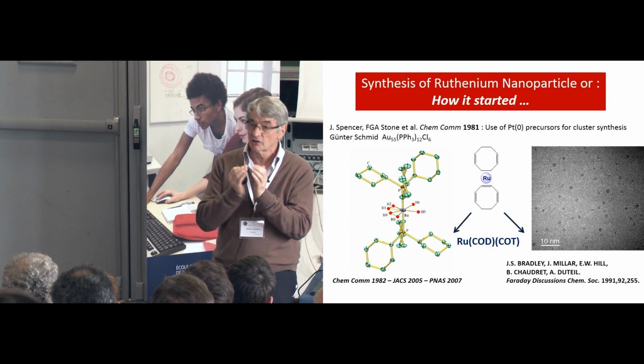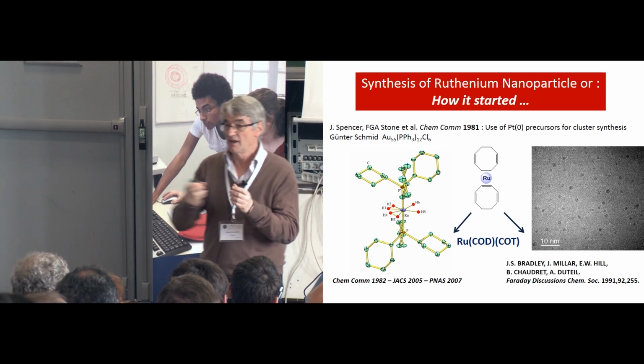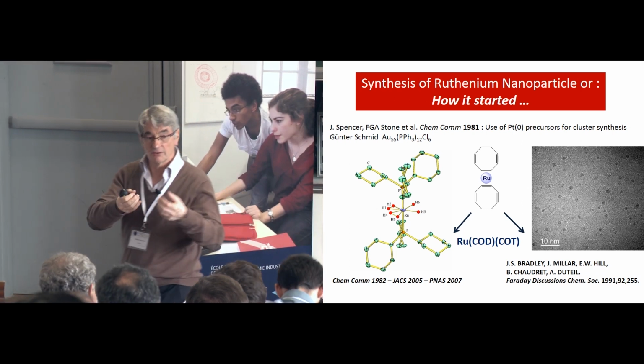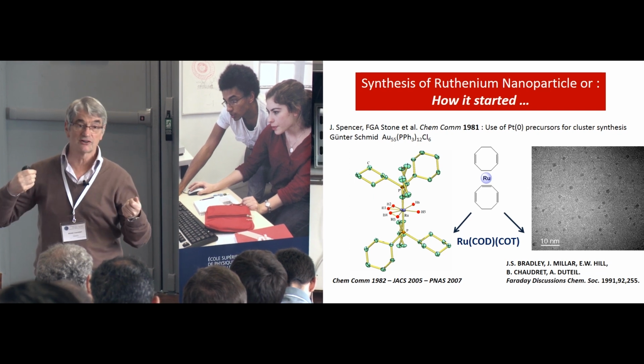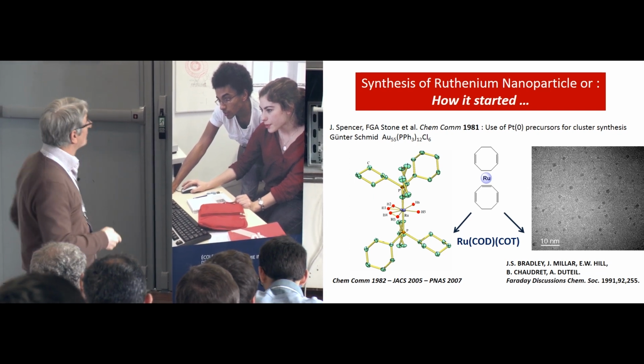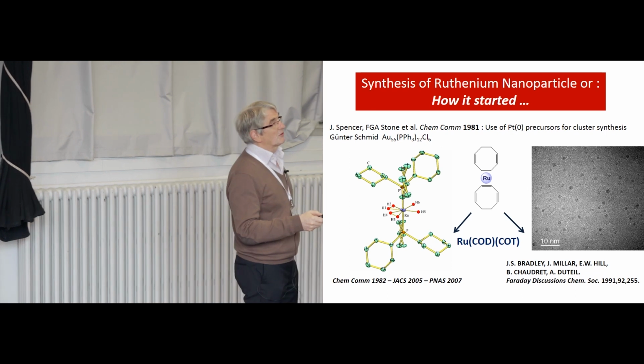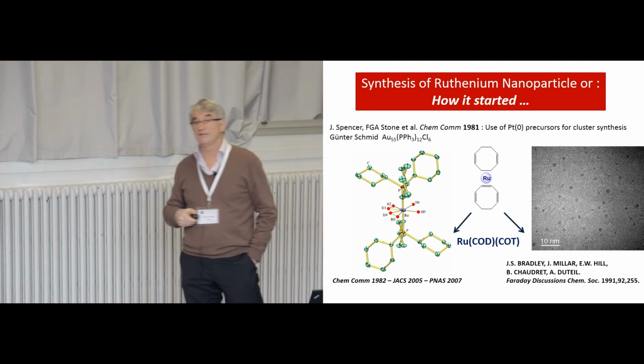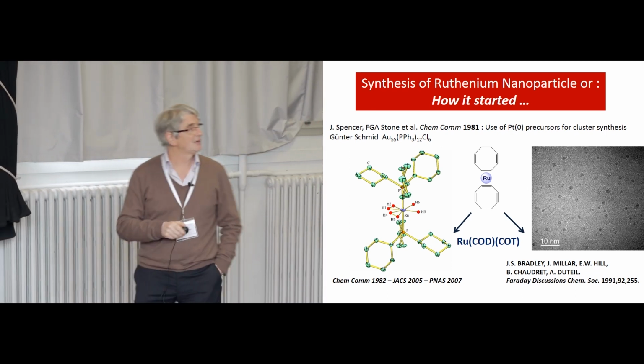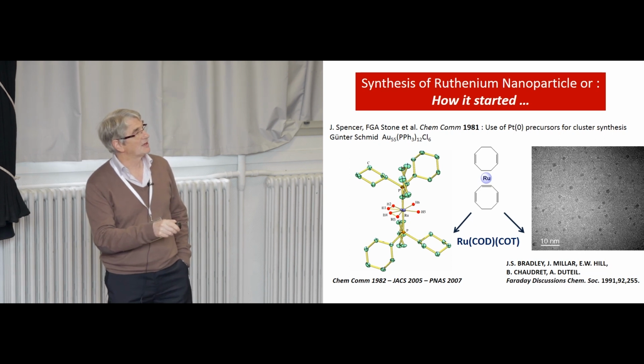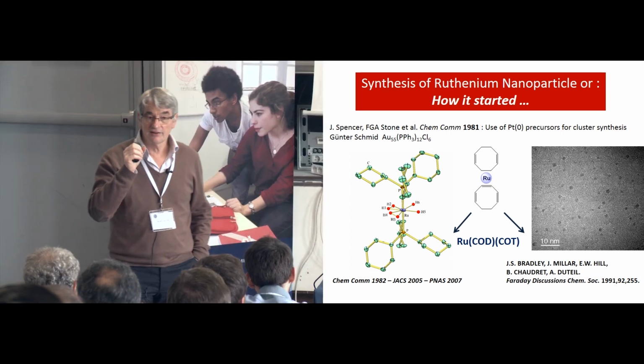Everybody was making carbonyl clusters of ruthenium, and they had no chemistry because the carbonyl would remove the electron from the surface of the ruthenium. So I took a precursor, zero-valent, prepared by Vitulli and Pertici in Italy: ruthenium cyclooctadiene, cyclooctatriene.